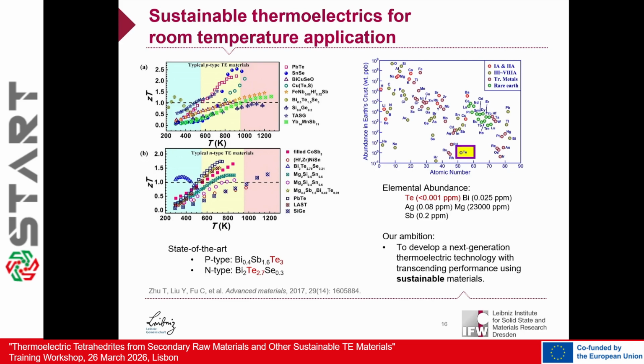If you look, for example, here are the two important components: the P-type bismuth antimony telluride and the N-type bismuth telluride selenide. These are the materials in 95% of all commercially available thermoelectric devices. A lot of the development in recent years is mostly at higher temperatures, so it's not really useful for thermoelectric cooling, for example. And a lot of these materials have not really been tested in devices.